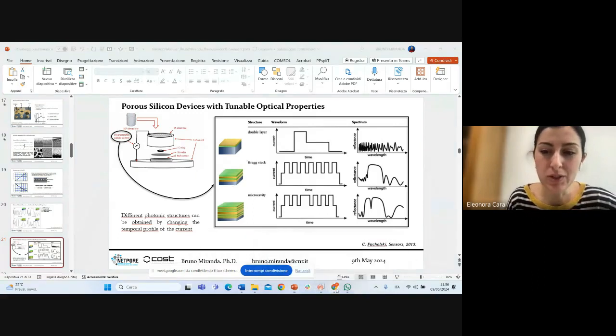What about long-term use and stability of your porous silicon substrates? If you don't passivate the surface of porous silicon, of course, maybe in 1 week it could degrade in air. But if you want to have freshly prepared porous silicon, you can store it for long times under vacuum or under argon or nitrogen gas. It should be quite stable. If you want to use it in ambient condition, you have to passivate with one of the passivation strategies I showed before. In this case, we do not see big variation in the optical response of the device.